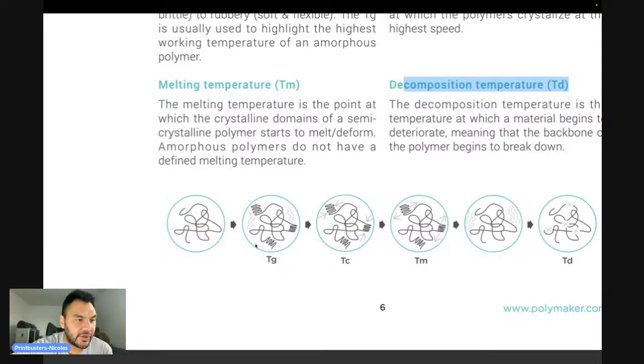Then now it has a much higher heat resistant temperature, right? So basically you crystallize it and you are going to destroy the crystal at Tm. So now the heat resistance simplistically will go from Tg to Tm, but actually it's like a gradient, right? Because from Tg to Tm, you will have the amorphous that is going to go softer and softer. You only have the crystals that's going to maintain more and more the overall integrity of the polymer.